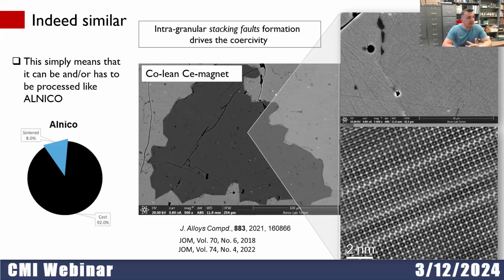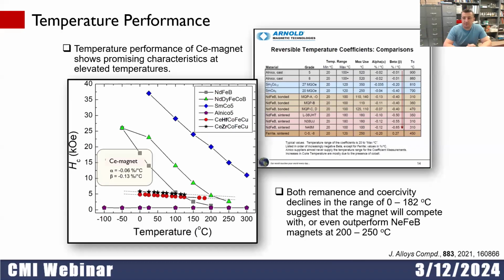This simply means that this system can be or has to be processed like alnico. And maybe you remember at the very beginning, I said the casting is more profitable or easier than the sintering. Why? Because casting doesn't have many processing steps. So it is interesting all of a sudden. And what is even more interesting is that the temperature characteristics of this system are also similar to alnico. So for example, you see that alnico is almost a horizontal line at the bottom of the left chart. And our system is not that horizontal, but still very stable.